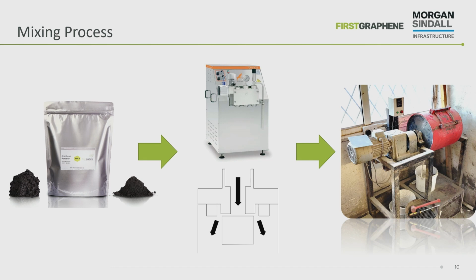And we passed it through that process, and what that does is it's a very tiny aperture in that mixer, and you apply about 1,000 bars of pressure to it, and as it goes through that tiny aperture, there's huge shear forces in there, and all those graphitic lumps, they get dispersed, and then you form your nice individual graphene platelets, and they're dispersed into the grinding aid.